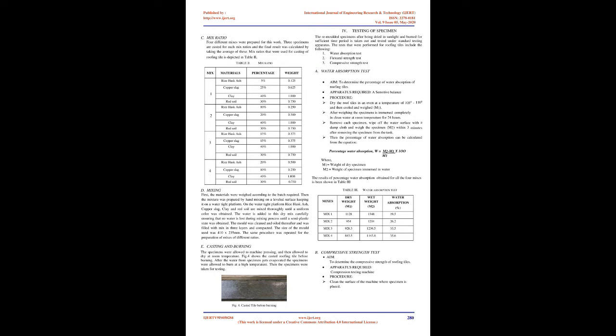Procedure. Dry the roof tiles in an oven at a temperature of 105–110°C, then cool and weigh, M1. After weighing, the specimens are immersed completely in clean water at room temperature for 24 hours. Remove each specimen, wipe off the water surface with a damp cloth, and weigh the specimen, M2, within 3 minutes after removing the specimen from the tank.